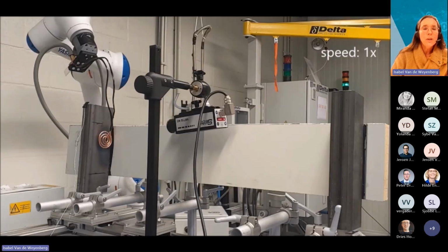So when we look at the example, what you see here is a cutout of the real composite panel. So it's about 2 meters wide. It's not a complete bus side panel. It's a cutout, and you see here 2 steel frames. Here you see the pancake coil that we use for our induction heating, and the black line here is the adhesive line.